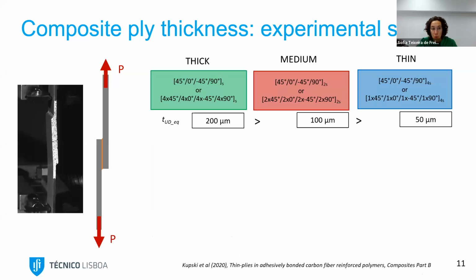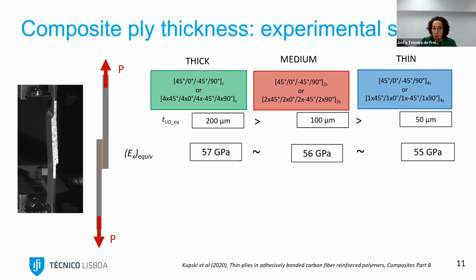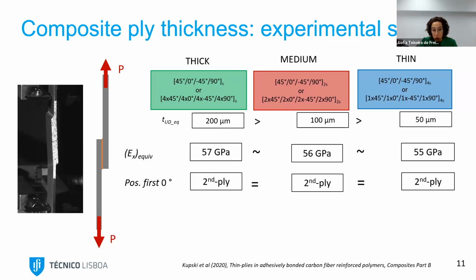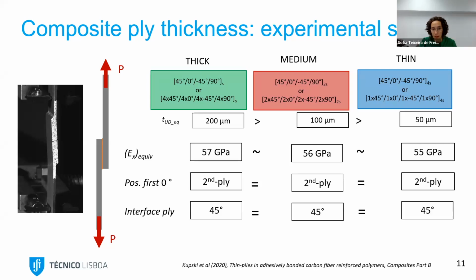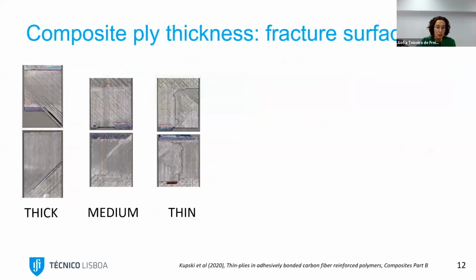In order to have only the parameter of ply thickness to interpret the results, we had to maintain most of the other parameters that we know also influence the damage, such as the bending stiffness of the composite, which was always the same. The position of the first 0 degrees layer, which also has an influence on the crack propagation, was always in the second ply. And the ply which is in contact with the adhesive was also always at a 45 degrees angle. So keeping these parameters constant is very important, so that we know we are only focused on the ply thickness for determining the results.